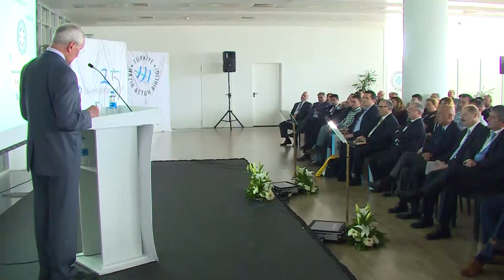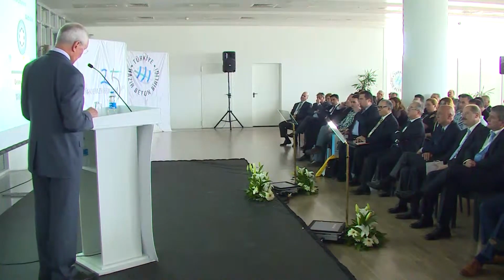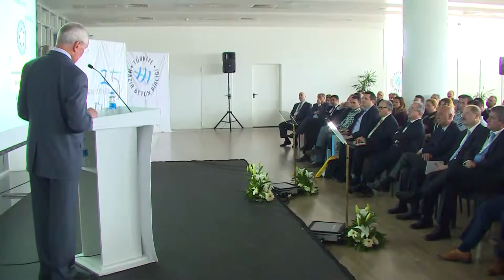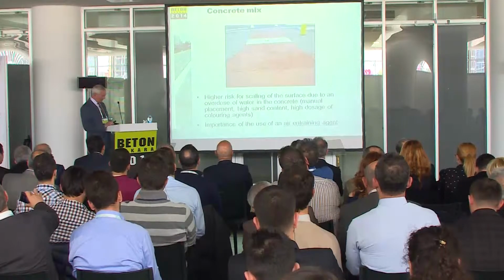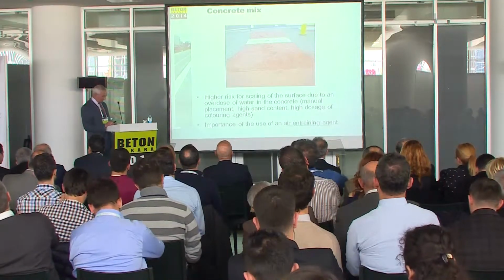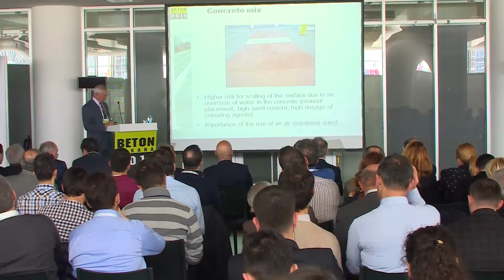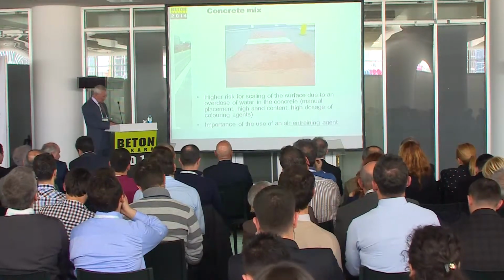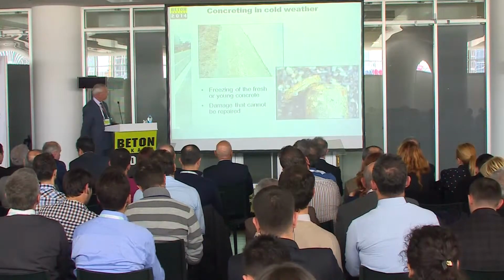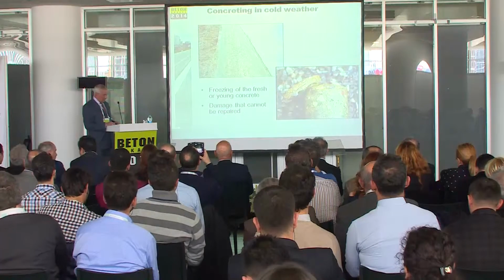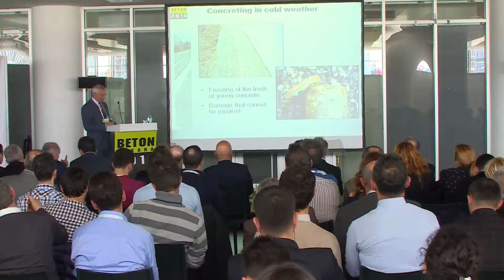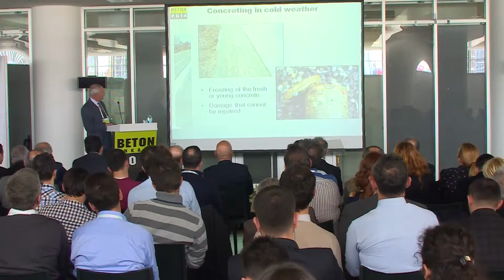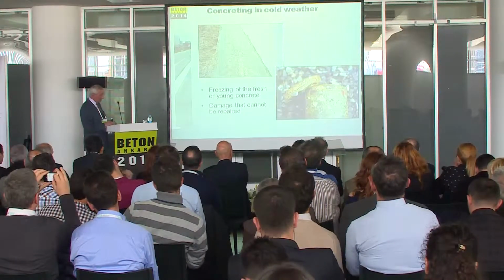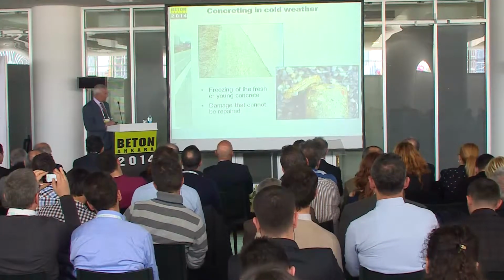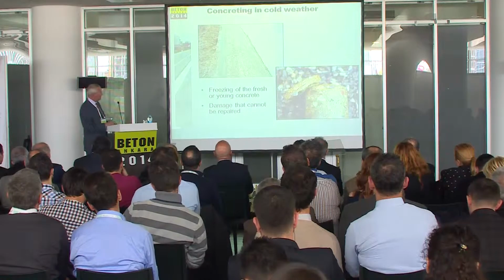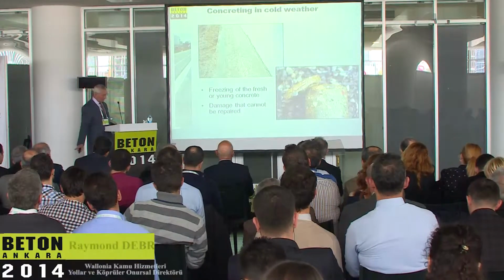Also surface damage due to an overdose of water with other aggravating factors: high sand content and too high dosage of coloring agents. To protect from frost, the use of an air entraining agent is important. Placing concrete in cold weather is dangerous. The protection can consist of, for example, non-woven geotextile, and without protection, damages are difficult and very expensive to repair.